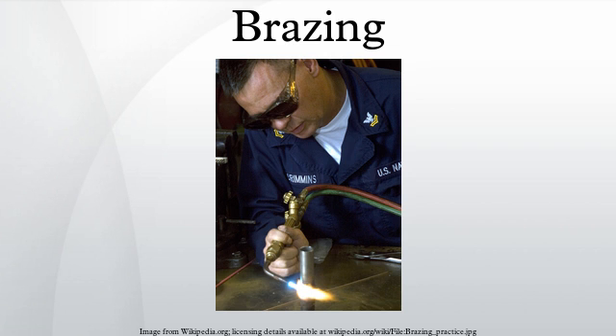Highly fluid alloys are suitable for penetrating deep into narrow gaps and for brazing tight joints with narrow tolerances, but are not suitable for filling larger gaps. Alloys with wider melting range are less sensitive to non-uniform clearances. When the brazing temperature is suitably high, brazing and heat treatment can be done in a single operation simultaneously.